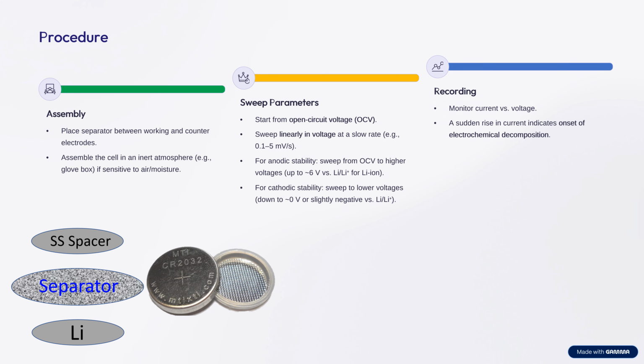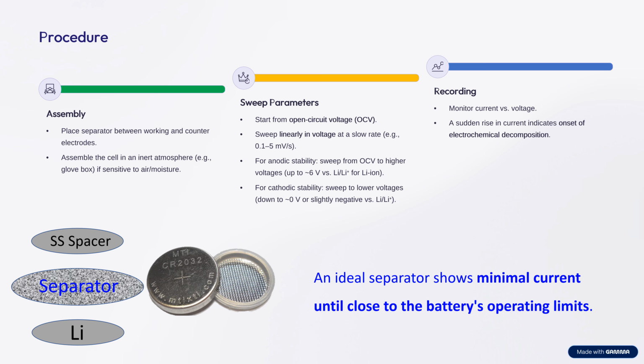Then you can monitor, you will get the current value and voltage value. You can convert the current into the current density by simply dividing the current by the area of the stainless steel spacer. If there is a rise in the current, then it shows electrochemical decomposition. It could be because of the electrolyte, it could be because of separator side reactions. So an ideal separator shows minimal current until close to the battery operating limits. If there is a current peak or spike, it's side reactions. If there is no peak, it means your separator is neutral. You can use it in the battery.